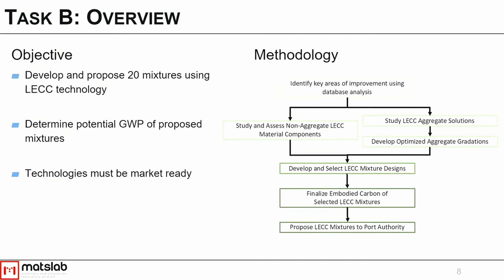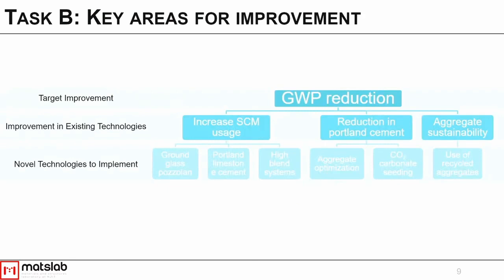From that, we studied ways that we can improve performance using aggregates, and ways that we can perform it using cementitious materials, and then we developed our mixtures and proposed those to the Port Authority. So we really broke this up into a few groups of technologies. The first group was to focus on supplementary cementitious material usage, so increasing the amount of cement that we are replacing in the mixture with other lower carbon materials. So newer technologies like ground glass pozzolan, trying to understand how Portland limestone cement might affect the system, and then really looking to push the boundaries of how much of these materials we could put into the concrete.